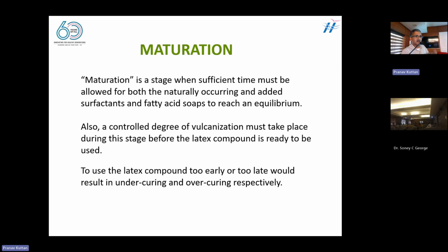So when it is kept in an idle stage for a period of time, it is undergoing a step called maturation. What happens in the maturation is that the crosslinks get adjusted. The monosulfidic, disulfidic, or polysulfidic linkages get adjusted as we require for our products. The properties which our products require, we design those crosslinks to obtain the good properties. So in order to have the latex for such a process, we keep it for a maturation period. Normally it is for a few days. When these crosslinks are matured, when the surfactants and the soaps added get into equilibrium, this will control the degree of vulcanization. That means the number of crosslinks between two carbon chains. This is the degree of vulcanization. That degree of vulcanization determines the final end properties. So this is done by subjecting the rubber latex for a period of maybe hours or days to a process called maturation.